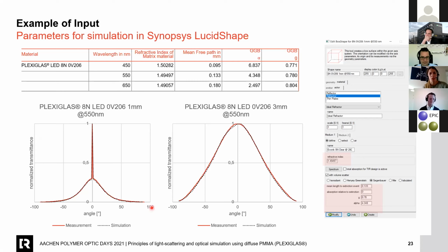So you decrease the thickness or the concentration. We increase the thickness of the plate to 3 millimeters and simulate the product again. And you see that we can simulate both thicknesses at the wavelengths. And now you can see as well that we don't have a hotspot anymore.